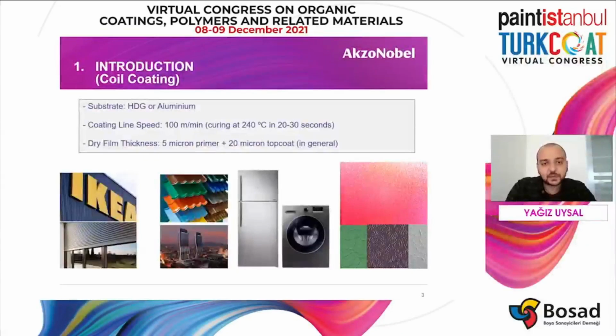Organic coatings are mainly used for protective and decorative purposes. After metals are coated in high-speed lines, they are wrapped as coil. Coil-coated metal is often considered more durable and more corrosion resistant since the metal is treated before it is cut and formed. Substrate is generally galvanized or aluminum, and it has very fast curing time, like 20-30 seconds, and it has thin coating layers such as 5 micron primer and 20 micron top coats.